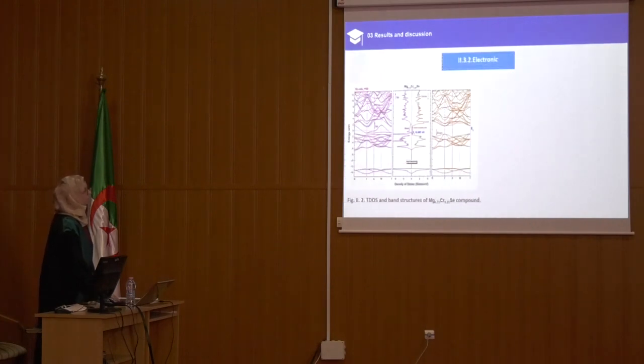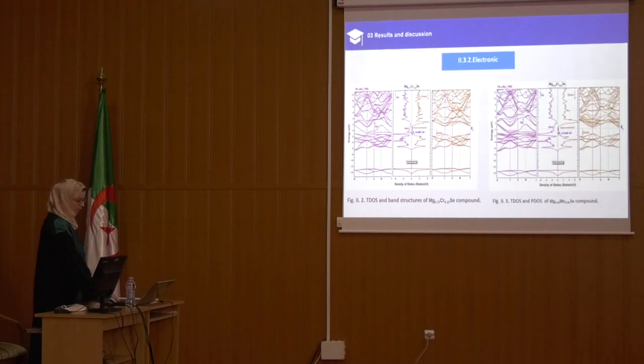For the electronic properties of these materials, both the band structure and the total density of states of the majority spin-up show metallic nature, with the presence of a large peak centered at the Fermi level.